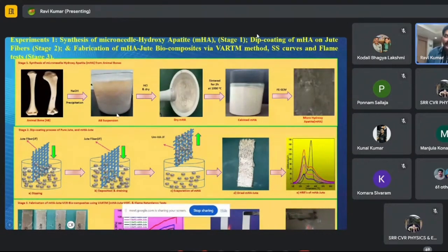That suspension we dried. Before drying, we treated it with hydrochloric acid and dried, and later we made it into powder. This is called dry MHA. This dry MHA we again sintered for 2 hours at 1000 degrees Celsius, and we got a clean powder. This is called calcinated powder of MHA. This calcinated powder, shown by FESEM, is clearly very crystalline, and it shows the microhydroxyapatite. That's why I gave the name MHA.